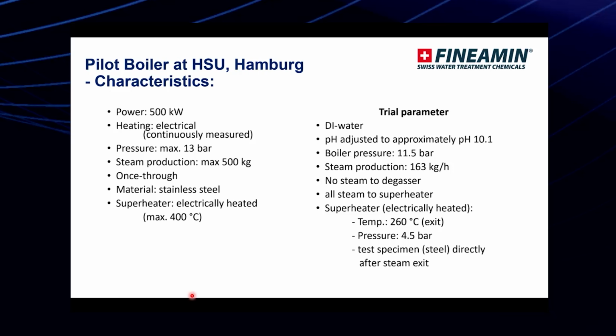In terms of the trial parameters, we will use deionized or demineralized water. The pH is adjusted to approximately pH 10.1. Boiler pressure is 11.5 bar, steam production 163 kilograms per hour, and there is no steam to the degasser, so that there will be no complication with the mass balance, because otherwise it would be very difficult to do the measurements. All steam will go to the superheater, which is electrically heated, and it exits at a temperature of 260 degrees Celsius, pressure 4.5 bar, and the test specimen sits directly after the steam exit.